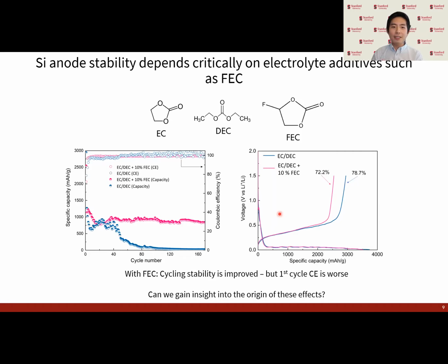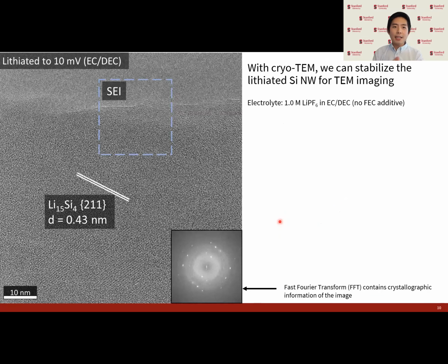So the question now is, with cryo-EM, can we figure out what this electrolyte additive FEC is doing to stabilize silicon, and what are the origins of these effects? So we can take our silicon nanowire platform that we've developed, and then we can fully charge or lithiate the silicon nanowire and prepare it for a cryo-TEM analysis, as shown here. So this image here is actually the first high-resolution image of lithiated silicon and its SEI ever recorded.